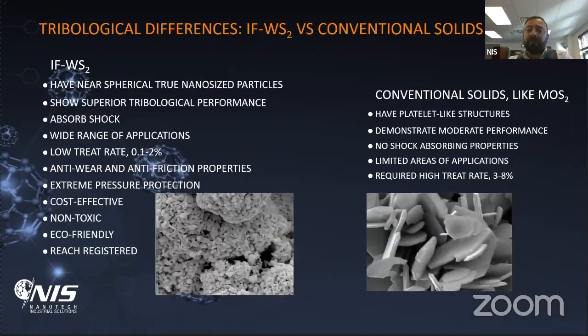So if we compare similar types of chemistries, like IF-WS2 compared to molybdenum disulfide of a regular shape, a legacy structure, we can see several very important benefits. First of all, tungsten disulfide of spherical shape, our IF-WS2, has a near spherical shape. It has very good tribological performance, and what is very important, it absorbs shock. I'm going to show you on the next slide the high resolution transmission electron microscopy video of how these particles absorb the shock, and all those mechanisms I'm going to talk about right now.